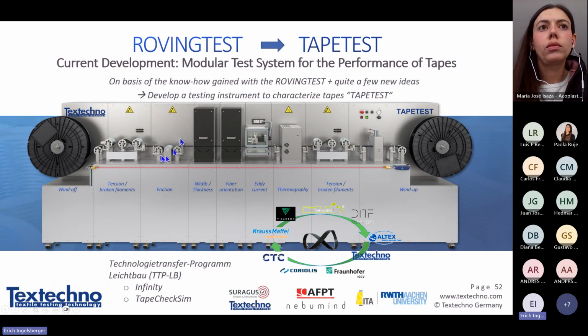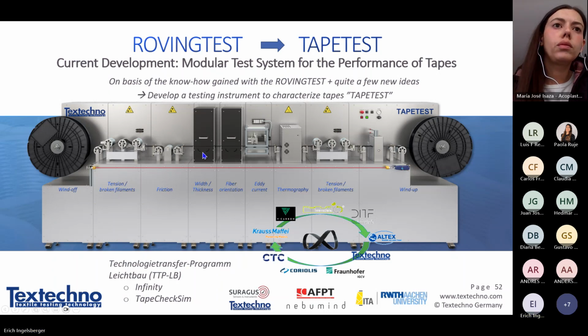We measure with a triangulation system the width and the thickness of the tape. We measure the fiber orientation - this is by eddy current, and this is by polarized light.